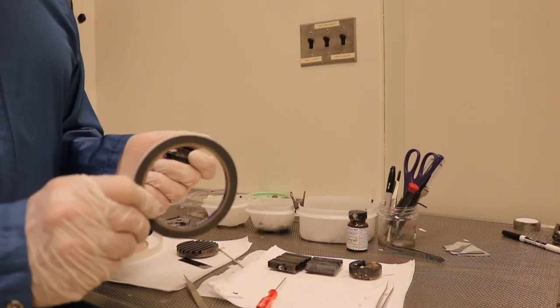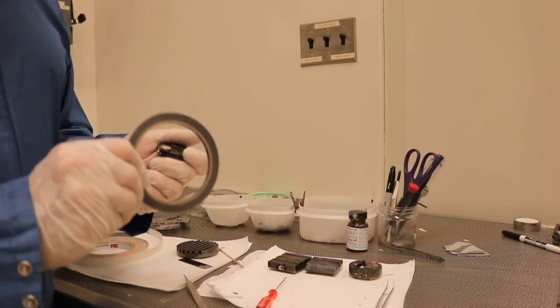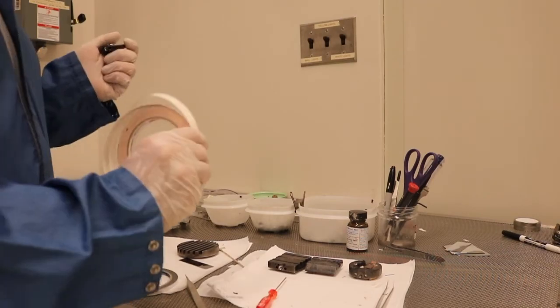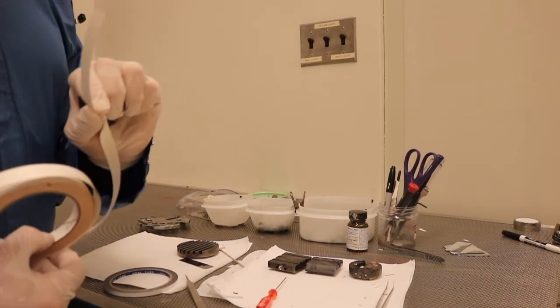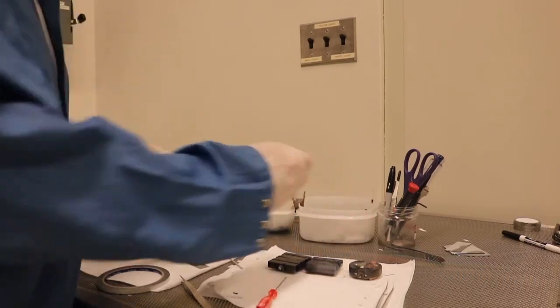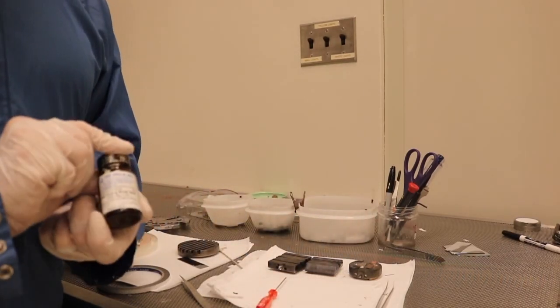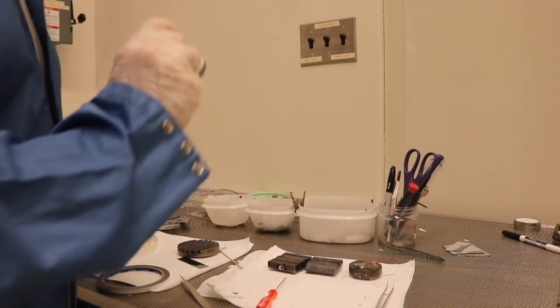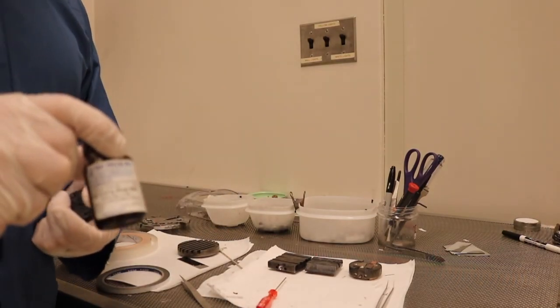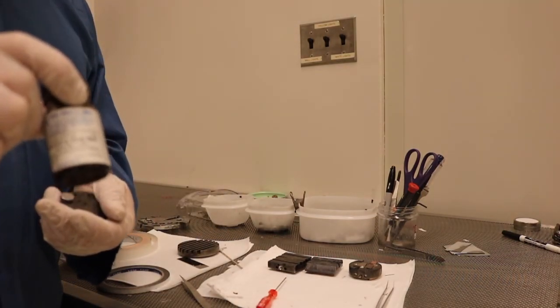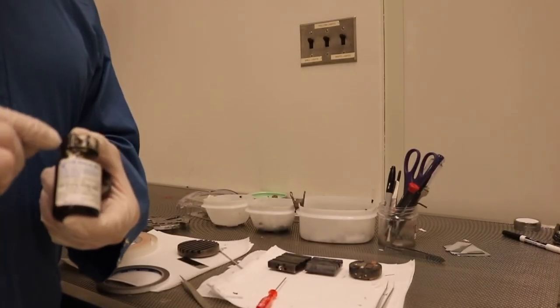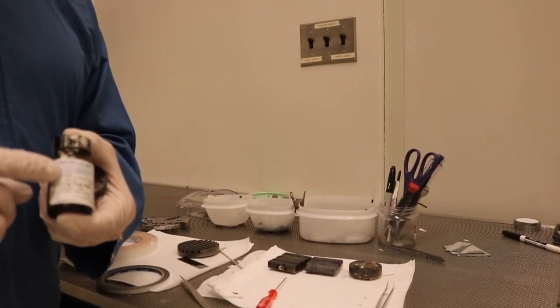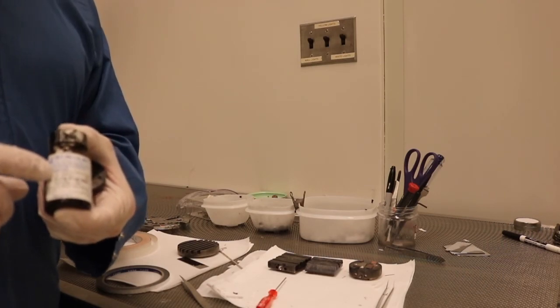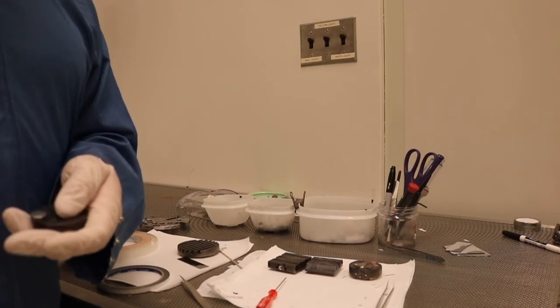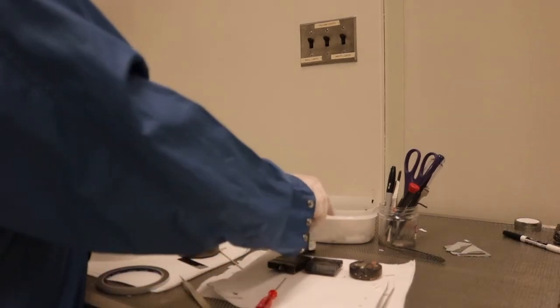The samples can be held on with double-sided carbon tape, double-sided copper tape, or alternatively, silver paste. The silver paste is probably the most conductive and easiest to remove your samples from the holders. The only problem with this material is that it will leave particles of silver behind. So if you have any other needs for your samples after the fact, this may not be the best choice.